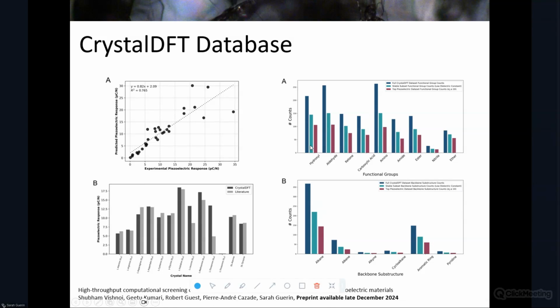And then the red bar is how many of those crystals have a piezoelectric constant of greater than 10 picocoulomb per Newton. So we've seen things like hydroxylation on the small scale increasing piezoelectricity, but now we can actually see the statistics on how certain functional groups give this property. And obviously there's a lot more work to be done on breaking down which of these are just common structural features of the molecules and which contribute to the bonding patterns that give rise to this property.